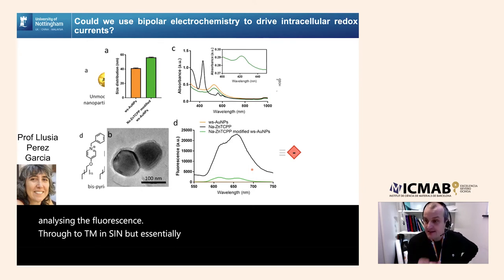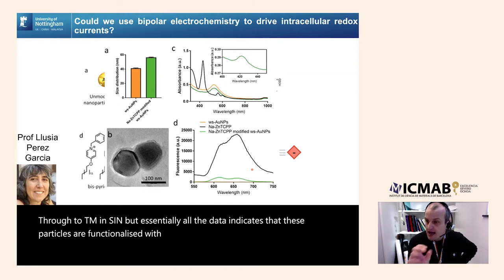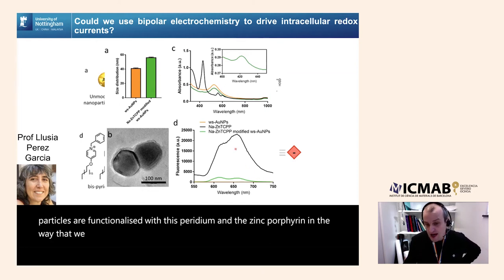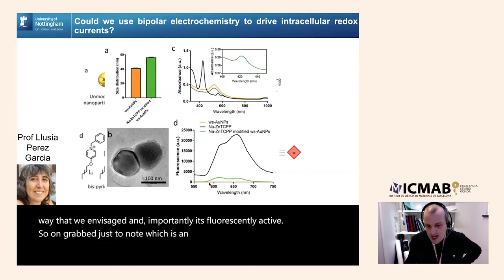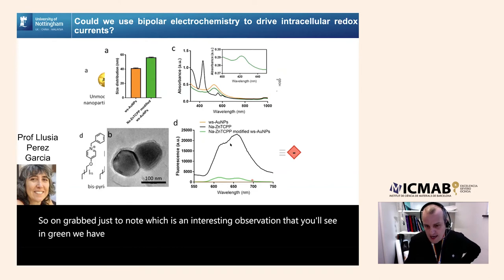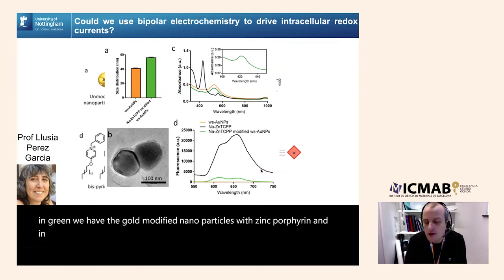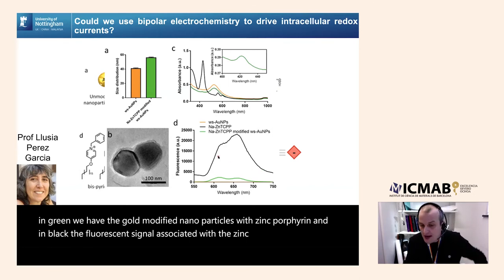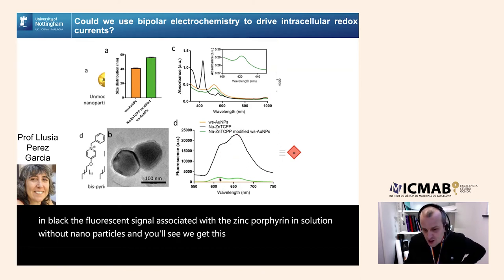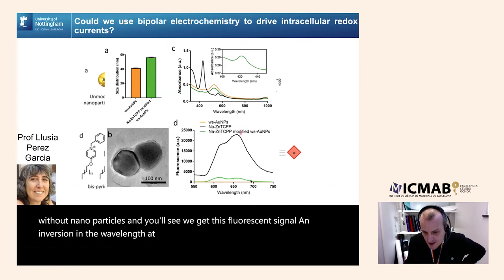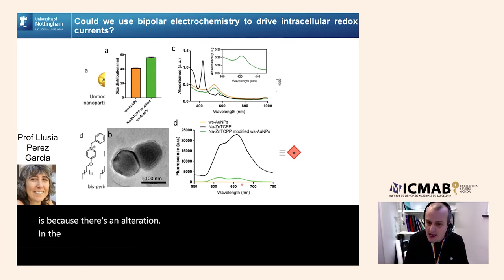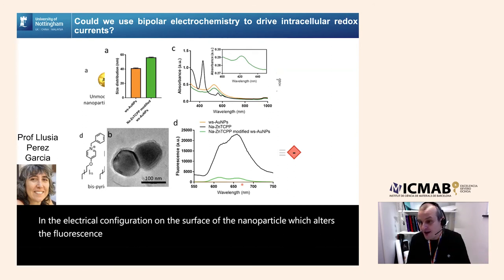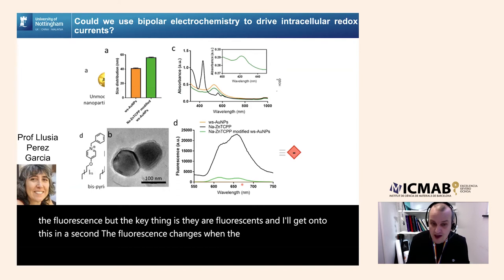But essentially, all the data indicates that these particles are functionalized with this pyridinium and the zinc porphyrin in the way that we envisaged. And importantly, it's fluorescently active. On graph D, just to note an interesting observation, you'll see in green the gold modified nanoparticles with the zinc porphyrin, and in black the fluorescent signal associated with the zinc porphyrin in solution without nanoparticles. And you'll see we get a shift in the wavelength at 610 versus about 675. We suspect this is because there's an alteration in the electrical configuration on the surface of the nanoparticle, which alters the fluorescence. But the key thing is they are fluorescent, and I'll get onto this in a second, the fluorescence changes when the zinc porphyrin's redox state changes.